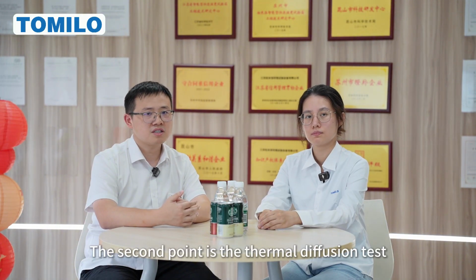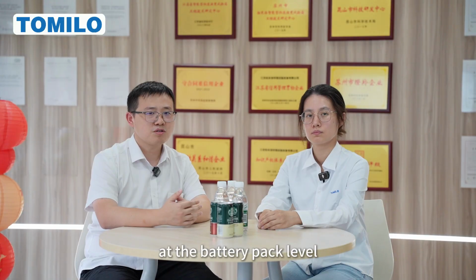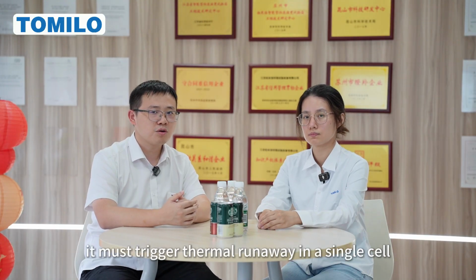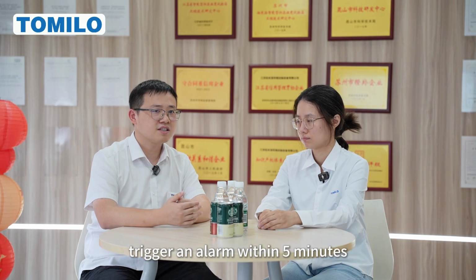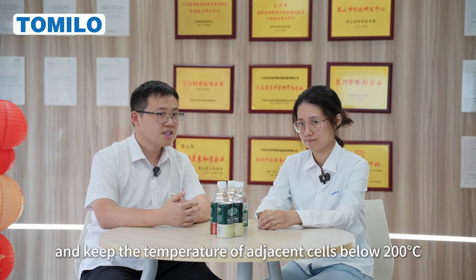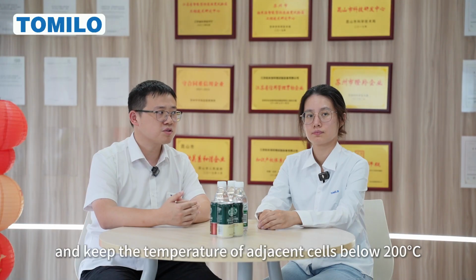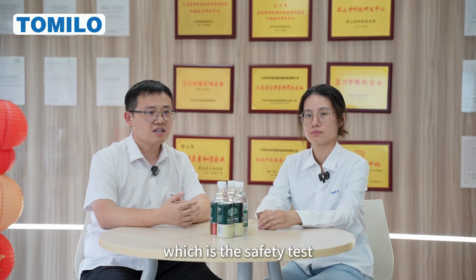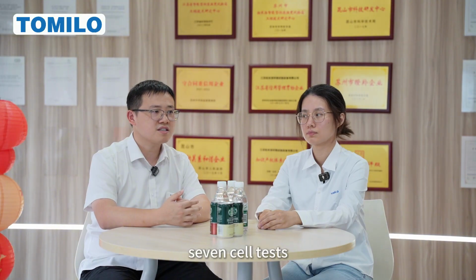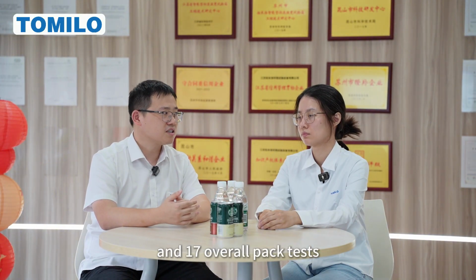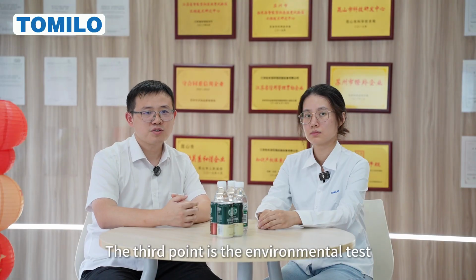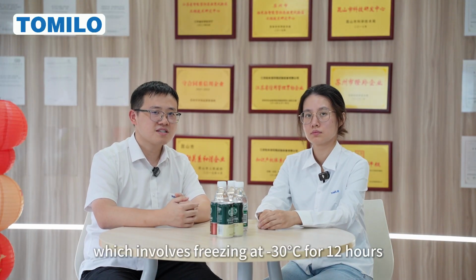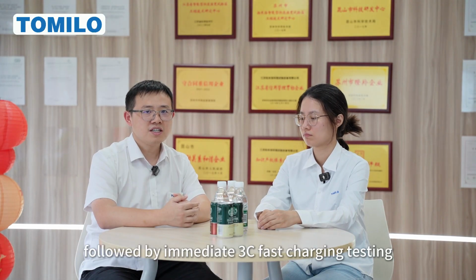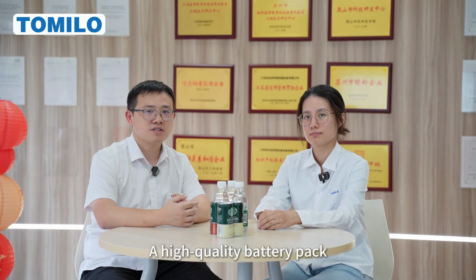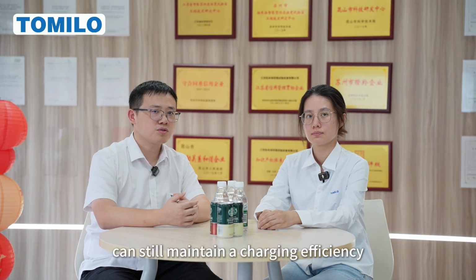The second point is the thermal diffusion test at the battery pack level. For thermal runaway at the battery pack level, it must trigger thermal runaway in a single cell, trigger an alarm within 5 minutes, and keep the temperature of adjacent cells below 200 degrees Celsius. The third point is our top priority, which is the safety test. It includes 7 cell tests and 17 overall pack tests. The fourth point is the environmental test, which involves freezing at minus 30 degrees Celsius for 12 hours, followed by immediate 3C fast charging testing. A high-quality battery pack can still maintain a charging efficiency of over 85% at low temperatures.